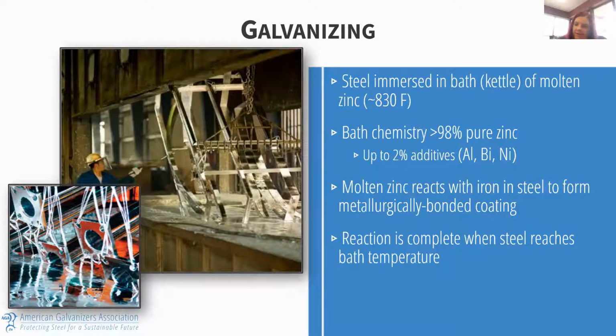While it's in the galvanizing bath, it's going to stay in there until it reaches bath temperature, typically about 5 to 7 minutes. The kettle operator would know when the steel has reached the bath temperature because the bubbling on the surface would dissipate. And while it's in the kettle, there's going to be a metallurgical reaction between the iron in the steel and the zinc in the kettle to form the galvanized coating. We'll talk a little bit more about that as we go forward.